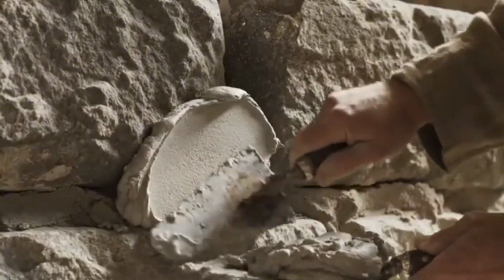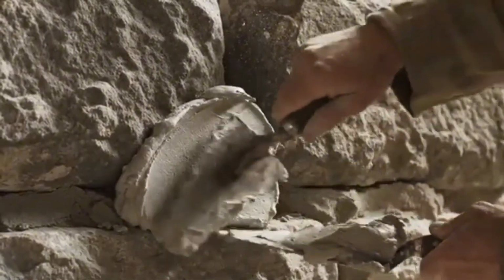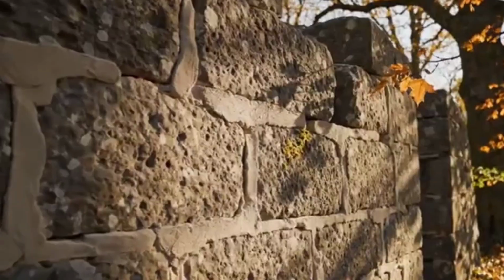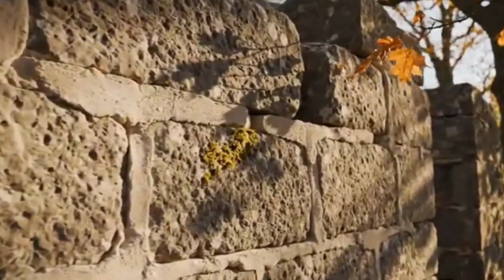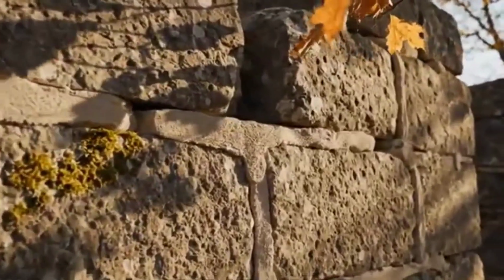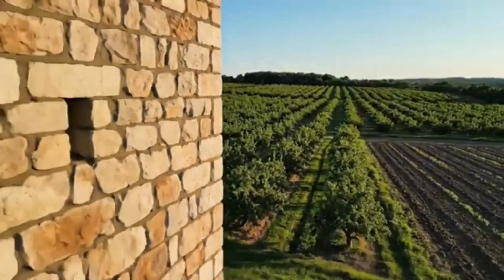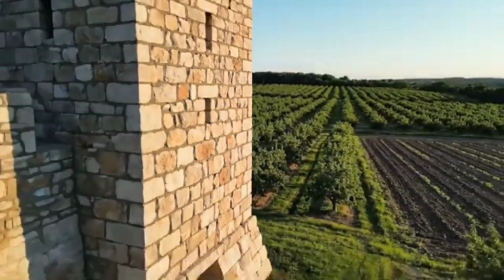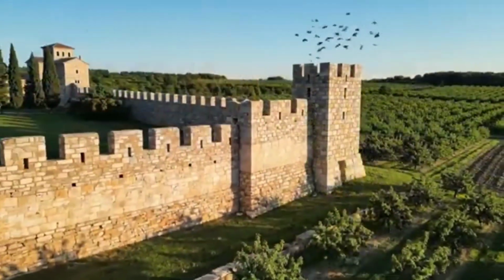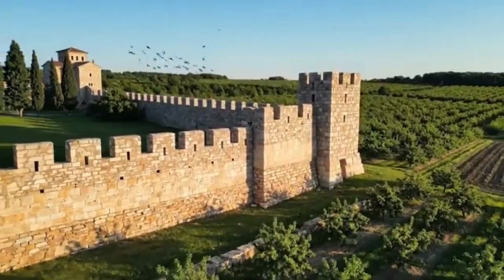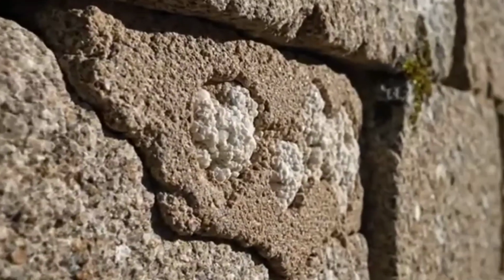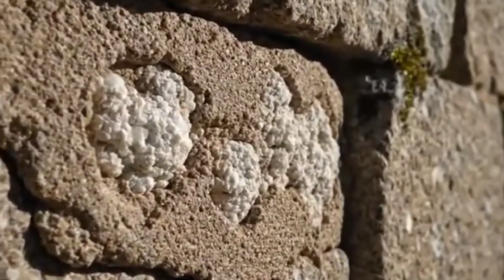The recrystallized calcium carbonate can also react with surrounding pozzolanic material to form additional cementitious compounds. The repair isn't a temporary patch, it's chemically identical to the original binding matrix. In some cases, the repaired zone becomes stronger than the surrounding material because the reaction fills micropores that existed since the original pour. Masic's team proved this in the laboratory.